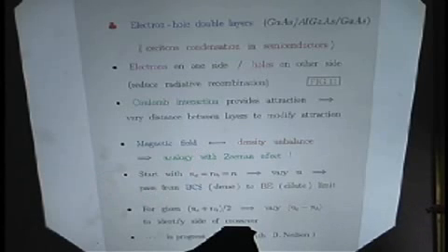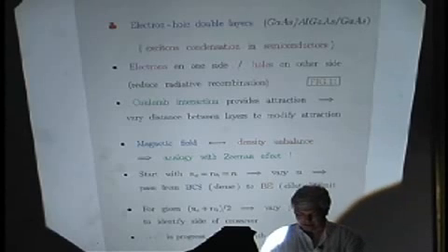So what we are doing in collaboration with David Neilson, University of New South Wales in Sydney, where I spent some time before coming here, you drive the crossover by varying the density, and then you may apply different gate voltages to the two sides of the sandwich. You may create a density imbalance, which will act effectively on this system as a magnetic field, and therefore can help you identify which side of the crossover you are in. Just a very last sketch.